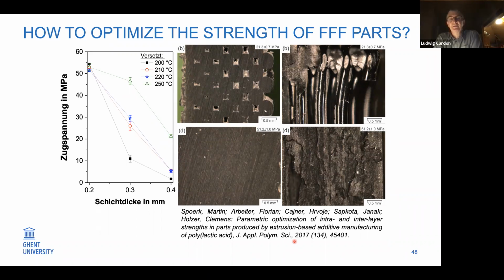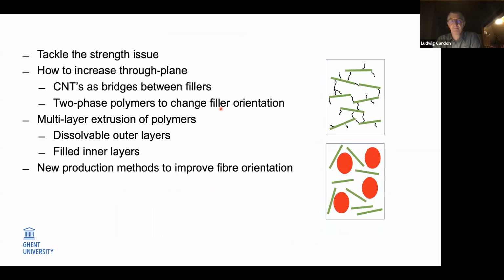It's not involved in this paper, but we have another paper together with Martin Spoerk, in which we integrated carbon fibers. One of the positive things to integrate carbon fibers or carbon black is the heat transfer, because then you don't have to go, for instance, to 250 degrees. You can process at 200, 210 degrees with carbon fiber filling for a very good heat transfer due to the absorption ability of your carbon fiber or carbon black fillers inside the blend. So you improve processing in combination with the mechanical behavior.